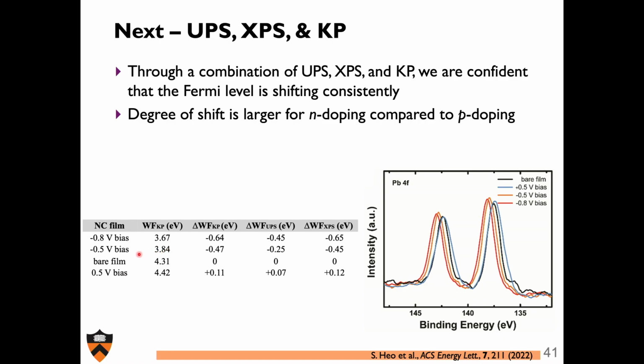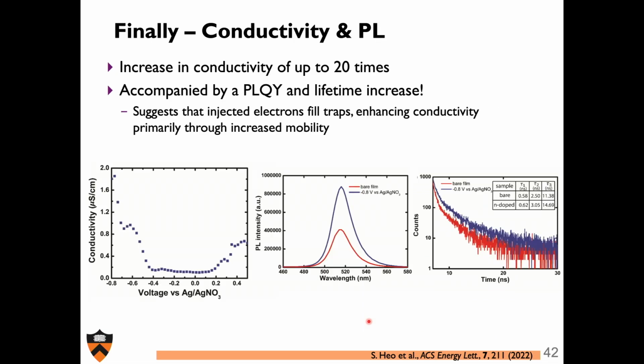You can get work function shifts of more than half an eV. And it's also seen in the core levels, not just the work function. This is work together with Antoine Kahn, who's an expert on electron spectroscopy and doping. And you can also see changes to conductivity. So you can see about a factor of 20 increase in conductivity when I n-dope the system. And that was coming together with an increase in PL. We said, oh, this is great.